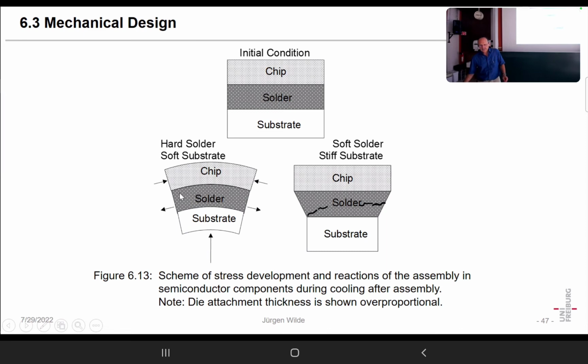On the other hand, if we have a harder solder or we have a sintered layer and more soft substrates or thinner substrates, then the whole thing will be coupled very strongly, but in that way it has a bimetal effect. The strongest effect, of course, would be if there would be no solder material at all, if it would be directly coupled. And in that way, these are the two cases which are relevant. Also, that case to the right explains to us why a solder will fail. On the other hand, the left case will rather explain why the chip will crack or why the substrate will crack.